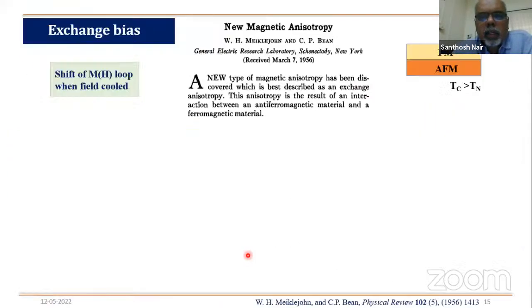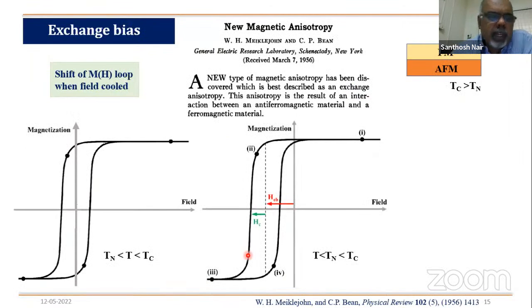Okay. So now, briefly, the idea was exchange bias. If you have an interface between an antiferromagnet and a ferromagnet, and then you cool it down, you will see a shift in the loop, which you call the exchange bias. So the ideal condition is that the TN should be less than the Tc. The ferromagnetism should happen initially, and then it can have an exchange bias because of the pinning effect at the interface between the ferromagnet and the antiferromagnet. So we have a system where we have a competition between ferromagnetism and antiferromagnetism, but not long range, but you have several nanoscale domains where these interfaces are formed. So will that show the exchange bias phenomenon?